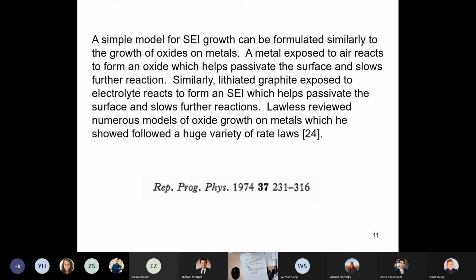And if you look at some of Dahn's papers on fast charge, you take every low viscosity solvent that you can imagine, and you mix it in with the standard electrolyte solvents, and you see if you get any kind of electrolyte that basically works. And you learn that some of them are just terrible because they react with the lithiated graphite and so on.